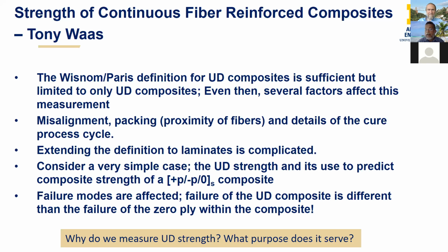And Silvestre alluded to some of those effects, which I'd like to repeat again. And those are misalignment, packing or proximity of fibers, and details of the cure cycle, which I haven't heard remarked, but I think Michael touched upon earlier. I can take a UD specimen, I can change the cure cycle, which I have done, by the way, in my laboratory, and do identical tests and find different values of failure. And the reason is this: the failure of the UD ply is not just a function of the fibers alone, even though the stiffness mismatch is large. It's also a function of the matrix, and the way it sets in is because of misalignment.